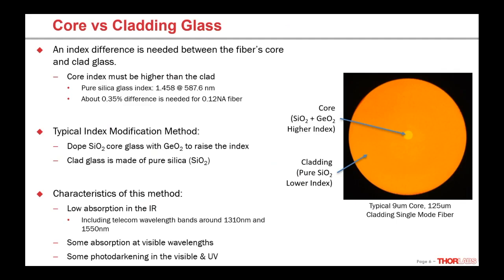In addition to being very pure, the optical fiber also needs to have an index of refraction difference between the core and the cladding. As physics dictates for total internal reflection, we need the core glass to have a slightly higher index than the cladding. For a typical 0.12 NA fiber — common telecom fiber — that index difference is about a third of a percent. One really common way we do this is the core is silica-based glass doped with a slight amount of germanium oxide, which slightly raises the index, while the cladding glass is made out of pure undoped silica.